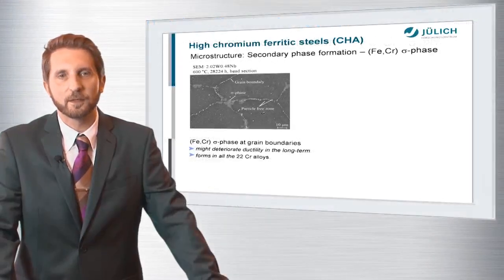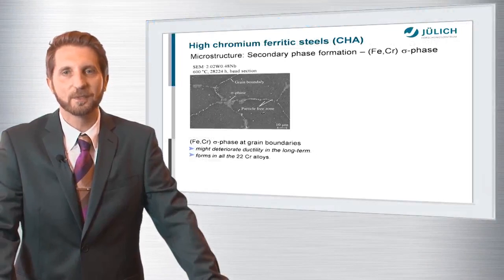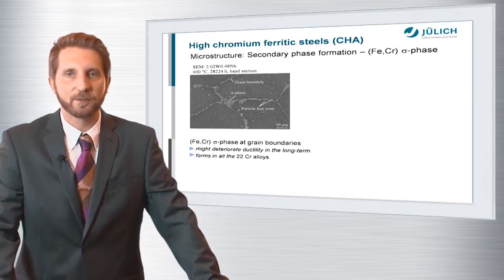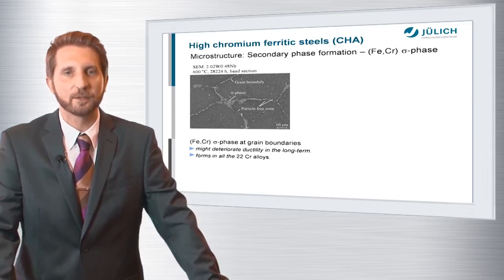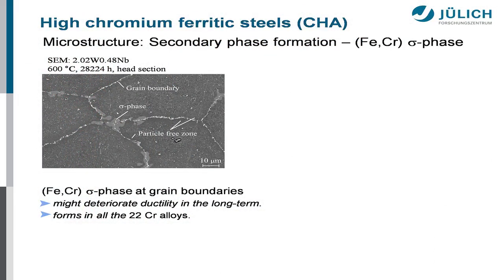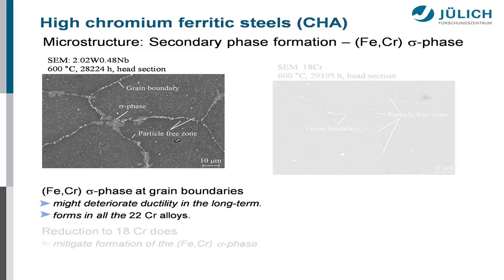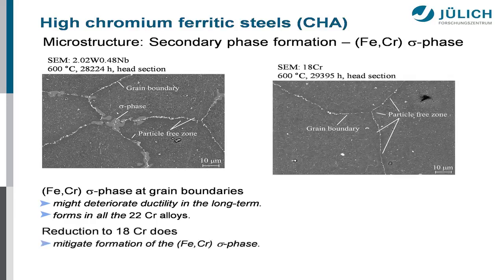Some more words on secondary phase formation. Always when you're talking about ferritic high chromium stainless steels, you always have to deal with the sigma phase, and this phase is very undesirable because it segregates preferentially to grain boundaries. And if it forms continuous films at the grain boundaries, it might deteriorate the ductility in the long term, which is very undesirable. Unfortunately, the sigma phase forms in all the 22 chromium alloys, like you see in the micrograph. But, and this is very beneficial, the cutback in chromium content to 18 weight percent helped a lot to mitigate formation of the iron chromium sigma phase.